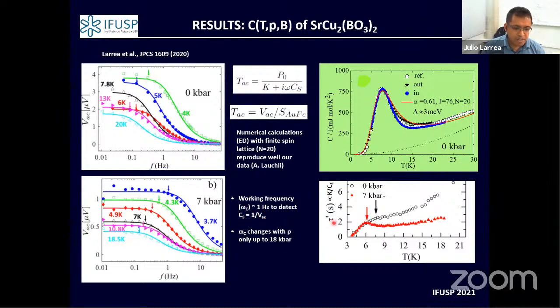What we did is for each pressure we set, we performed a frequency scan throughout. With that, we avoided the specific heat simply maxing out due to frequency dependence just to maximize it. So our measurement has high accuracy in determining the heat capacity.